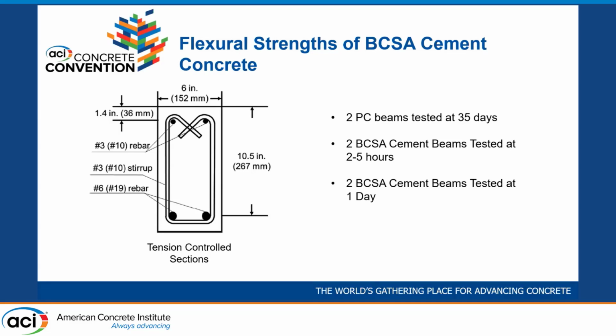And the reason that we did 1 day is because at this age, their strengths were very similar to the Portland cement beams. So we were testing the very early strength of the beams, as well as the strength of the beams when the compressive strength was similar to our Portland cement controls.